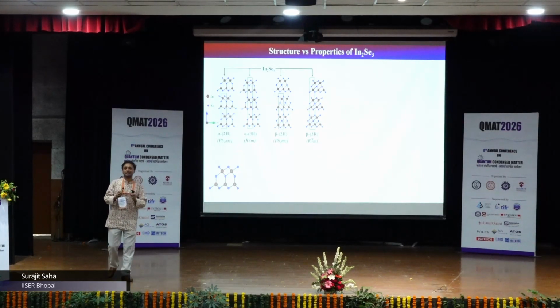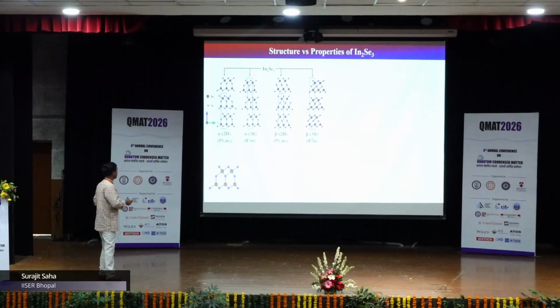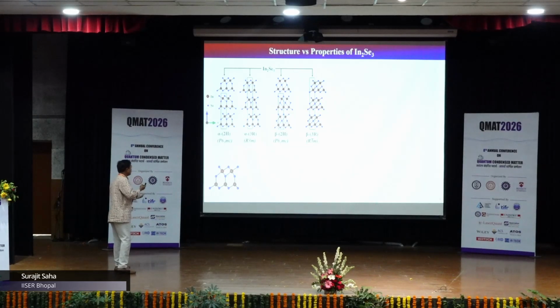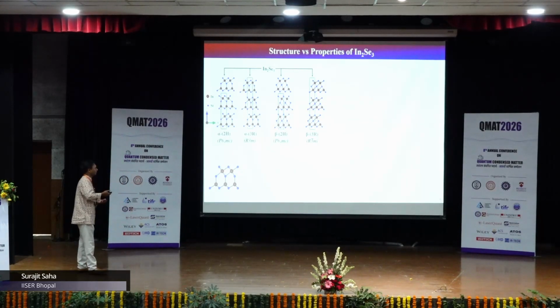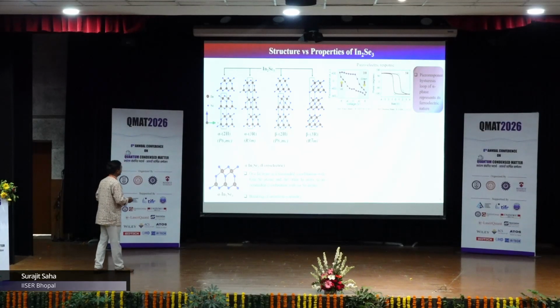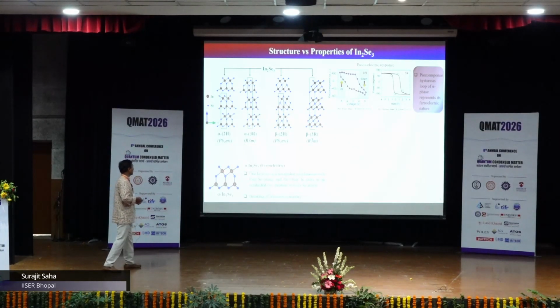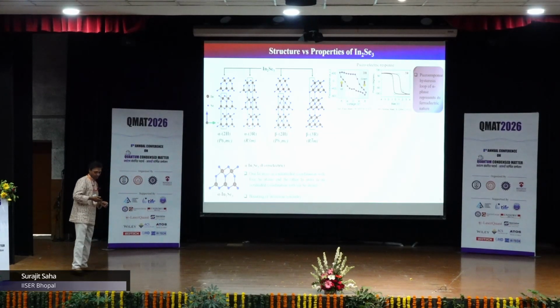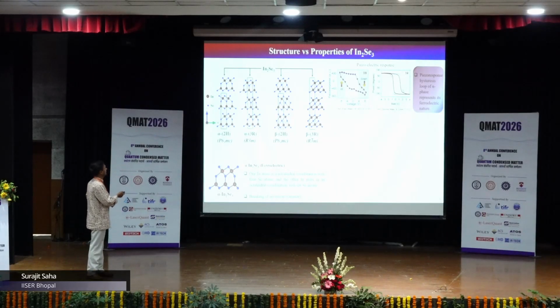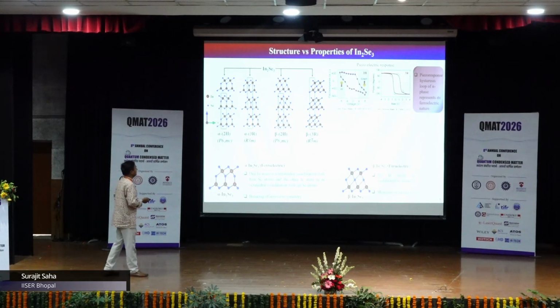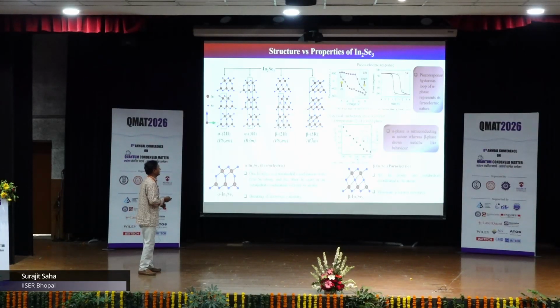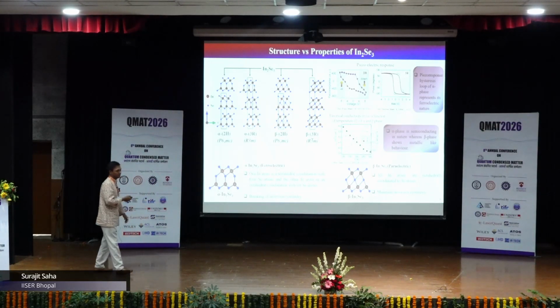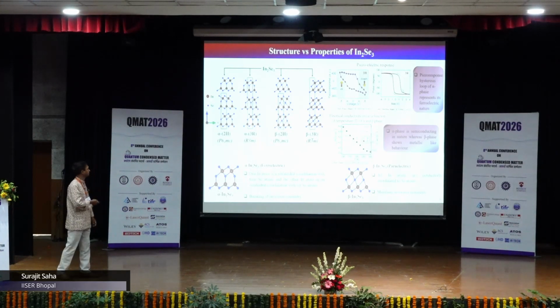So this is the distinction between the two structures, and correspondingly the other polymorphs where 2 layers or 3 layers would be stacked. And the alpha systems are ferroelectric, basically because it breaks the inversion symmetry, and there are various reports on its ferroelectricity in the literature. And the beta phase is basically paraelectric, because it retains the inversion symmetry.